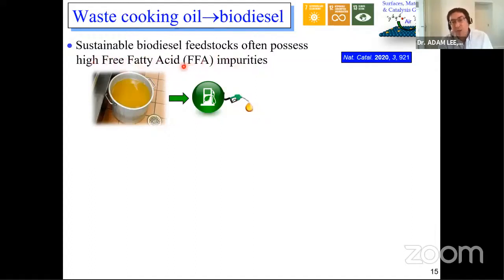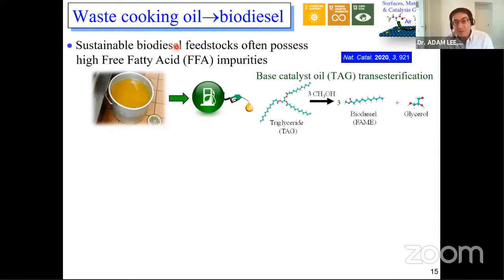Now, traditionally, when you make biodiesel, you take a bio-oil and you use a base catalyst to do the transformation. So here's an example of how you make biodiesel normally. You take a pure oil and you transesterify it using an alcohol to make biodiesel and some glycerol. So this is a base catalyzed reaction. And that's a problem because base catalysts don't like acid impurities. If you expose a base catalyst to this used cooking oil, it instantly deactivates the catalyst, it poisons it.